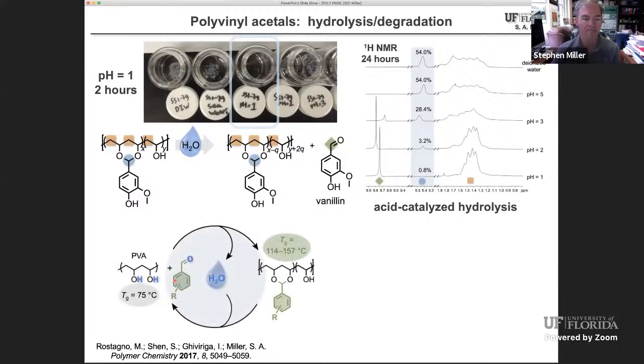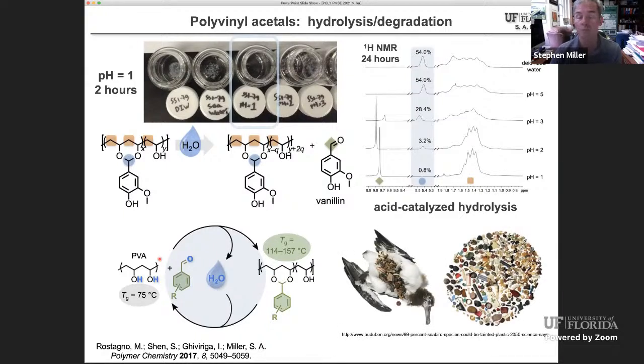But nonetheless, this seemed like a way to take a relatively inexpensive polyvinyl alcohol, which shouldn't really contribute to the polymer contamination problem, attach a bioaromatic aldehyde, utilize it for its high glass transition temperature, and then somehow take it back to the starting materials. So where on earth would this be useful, and how are you going to get this to degrade in the environment? There's not that many places on earth where the pH is low enough for this to happen, but this bird's stomach is one of them.